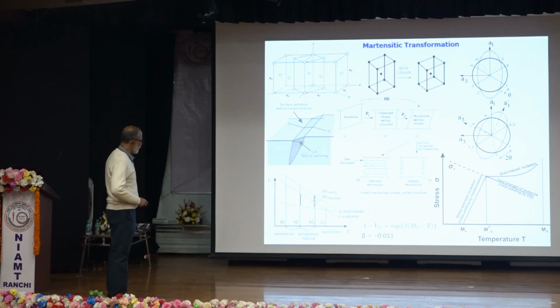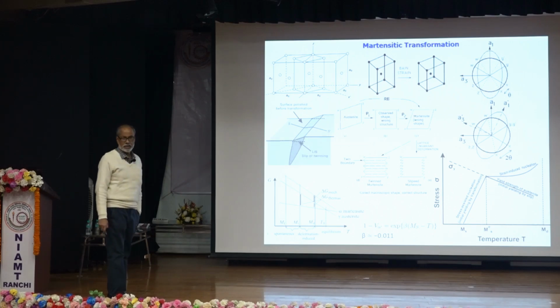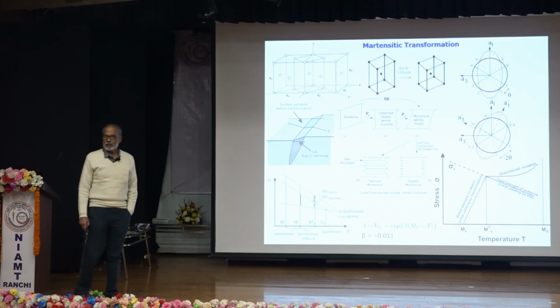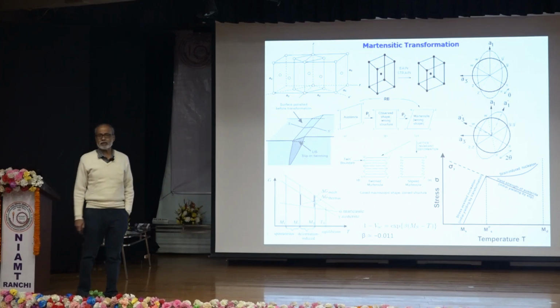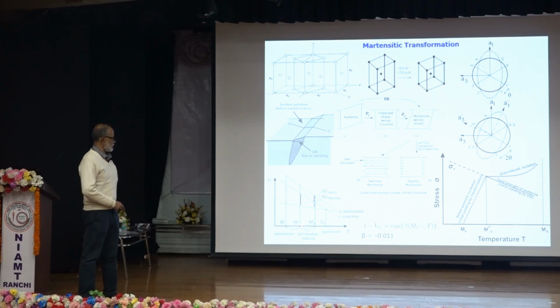But what about shear? Shear occurs at a temperature above martensitic start temperature. And if you go at a temperature above martensitic start temperature, you will find the thermal driving force is less than that minimum required for martensitic transformation. This is minimum driving force, minimum energy required for martensitic transformation. But at any temperature above Ms, the driving force is much less than required. So that can be compensated by mechanical driving force. The shear compensates the deficiency in driving force and completes the necessity of the driving force required, right? So application of shear may cause martensitic transformation above a temperature Ms, right?